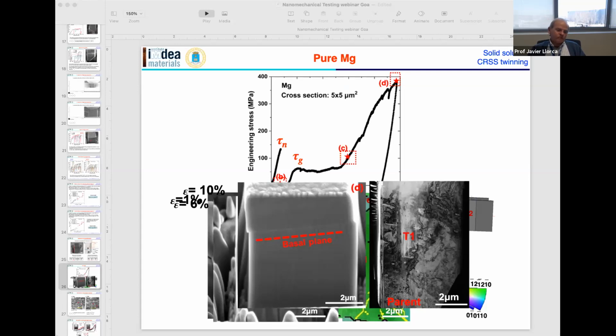So at the end of the day, these are the results of our investigation. This is the critical resolved shear stress for twin nucleation as a function of the pillar size. These are the values in red for pure magnesium, magnesium 4% aluminum, and magnesium 9% aluminum. And those are similar values for the case of twin growth. As you can see, if you put up to 4 atomic percent of aluminum, it doesn't change very much the critical resolved shear stress for twin nucleation and growth. But when you go to 9% aluminum, there is a clear increase. The effect of micropillar size on the mechanical behavior is negligible for micropillars with dimensions above 5 microns.